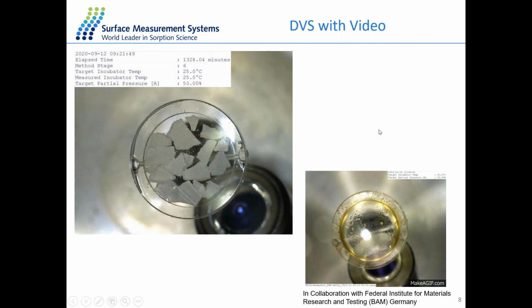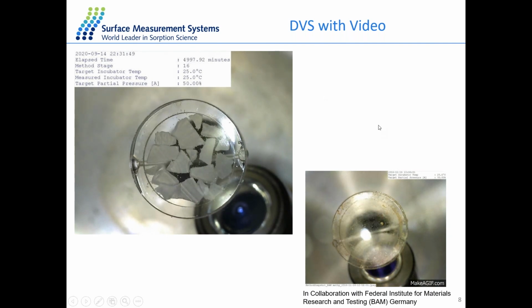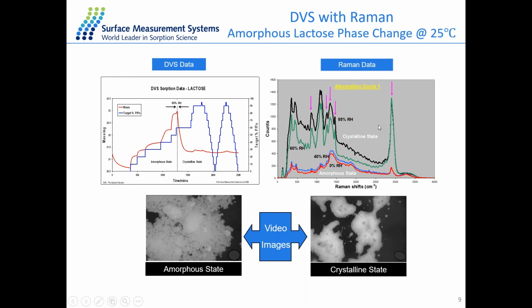Another accessory to be integrated with the DVS technique is that we can put a Raman spectrometer with the DVS, and we can collect the Raman spectra at the end of each humidity stage when it's reaching equilibrium. So for example, here we have an amorphous lactose sample, and we perform 2 cycles of water sorption and desorption experiments with this amorphous lactose sample.